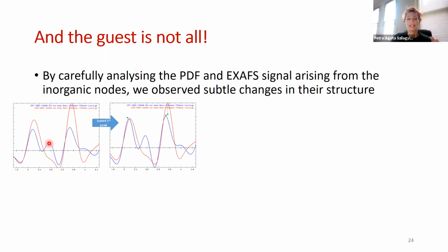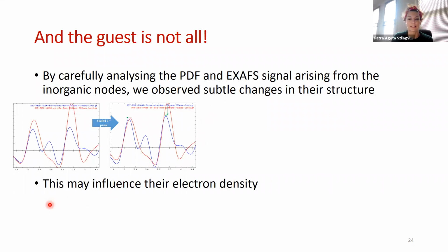So this is purely the interatomic distances in the inorganic nodes, shown in red before and in blue after the addition and reduction of palladium. You can see that there is a shift. This is just normalized, the difference between these two data sets. There is a shift in the zirconium-oxygen and zirconium-zirconium interatomic distances, and this is important because it may influence the electron density in these small nodes.